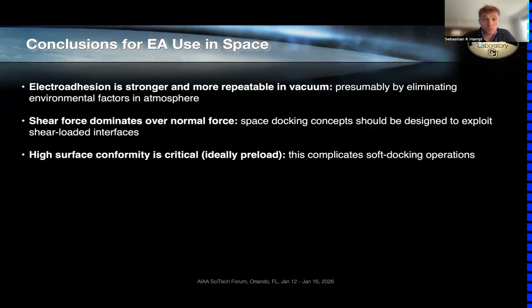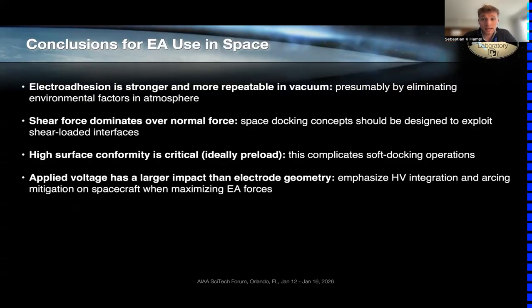We also found that surface conformity is critical, and this is typically achieved in terrestrial applications by preloading. This is complicated in space because, especially for soft docking applications, you have no chance to preload. And this is just something to keep in mind when designing these systems, that this might be a bottleneck. From our studies, what we found is that the applied voltage is much more important than the electrode geometry. So we believe that it would be much more important to design these systems for a higher voltage instead of trying to optimize electrode geometries, because they don't play as much of a role.